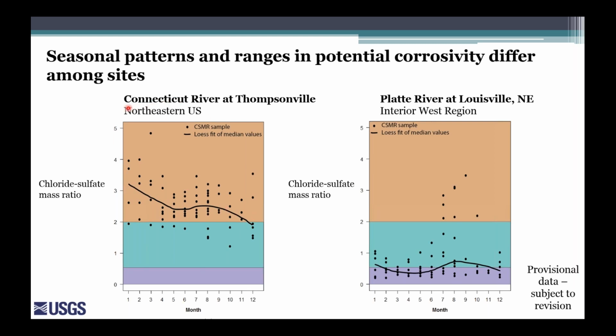So first, if we look at the Connecticut River at Thompsonville on the left-hand side of the slide, we see that the chloride to sulfate mass ratio peaks during the winter months. And this is most likely due to the use of road salt as a road de-icer in that particular basin. There's a secondary peak that occurs late in summer, which can be explained in at least a few different ways. Late summer in the Connecticut River is a very low flow time of the year, and so the water that is in the stream at that time is dominated mostly by either groundwater or by water that is coming out of wastewater treatment facilities. And so it could be that the wastewater treatment facilities have a relatively high chloride to sulfate mass ratio and are influencing the chloride to sulfate mass ratio at that time of the year.